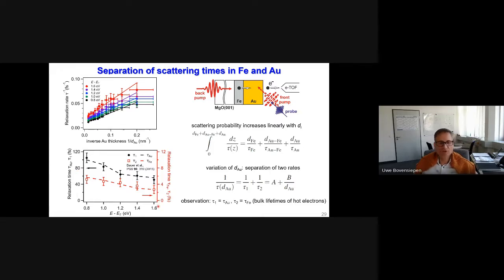And now let's compare this to literature data for bulk gold and bulk iron. And these are the dashed lines. So the dashed line here in red is the literature relaxation time in bulk iron, and the black line is literature data for bulk gold. And this is what we measure. So in this heterostructure analysis, where we bring in the electrons from iron, inject them in gold, and let them propagate through gold, we can investigate buried media, and by variation of the gold layer thickness, we really become able to separate the processes in these two materials. So this is the future impact that I expect, investigating here buried media and interfaces with photoelectron spectroscopy.